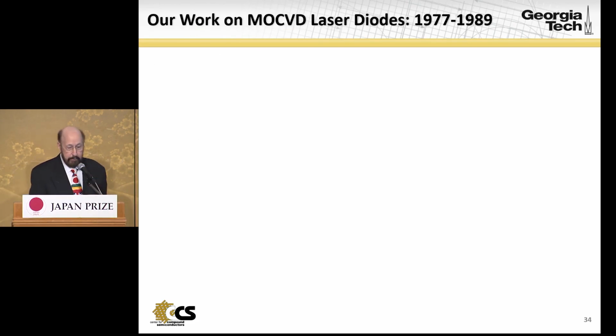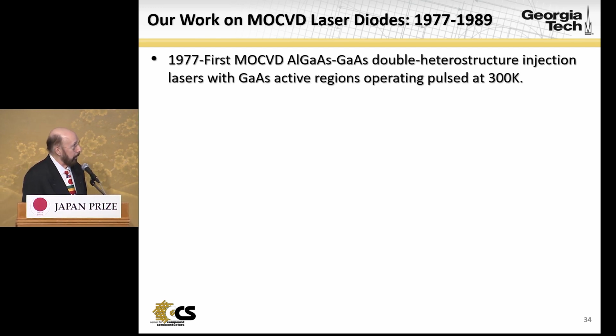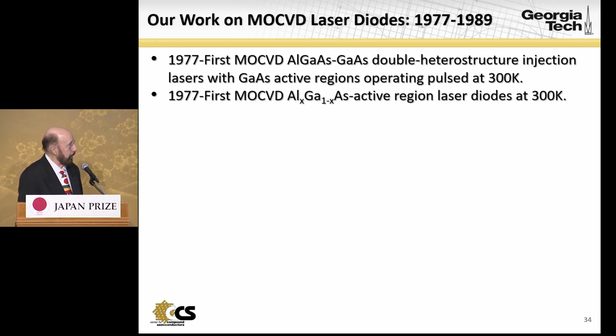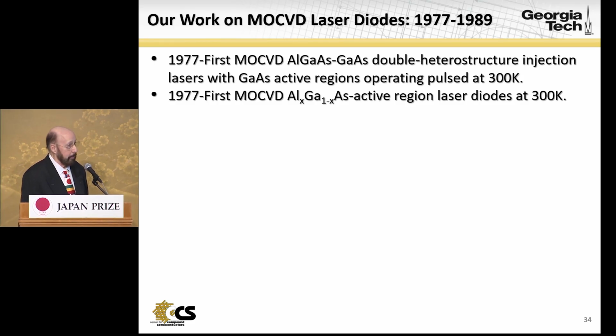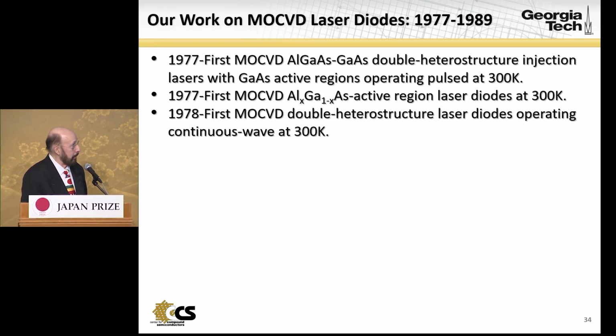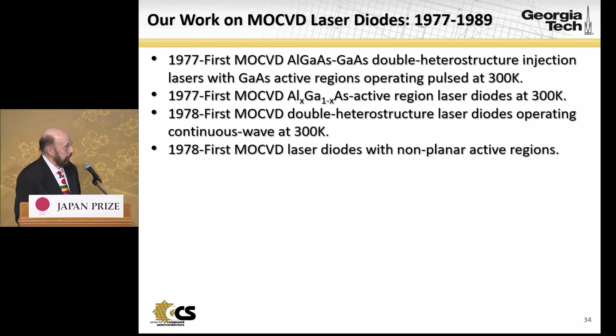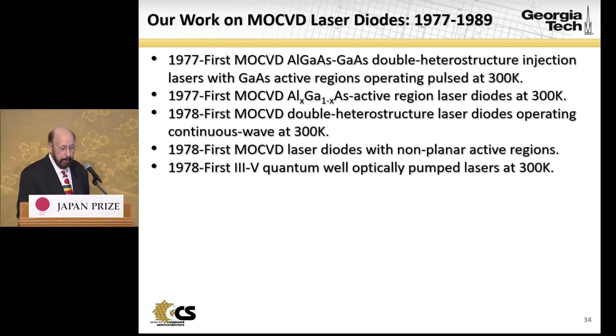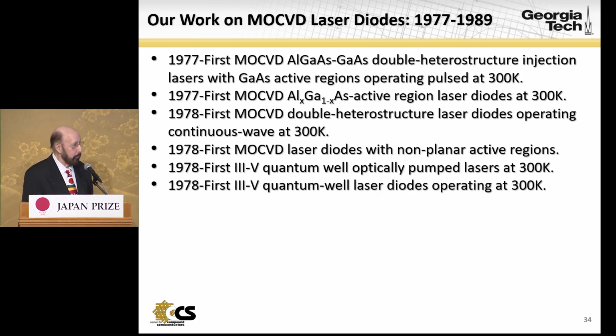So in this next period, we developed quantum well laser diodes in many different ways, beginning in 1977 with the first double heterojunction lasers with gallium arsenide active regions, pulsed at room temperature. Then the first MOCVD lasers with aluminum gallium arsenide active regions emitting at shorter wavelengths. Then in 1978, the first double heterostructure lasers operating continuous wave at room temperature. And also in '78, the first MOCVD laser diodes with non-planar active regions, the first quantum well optically pumped lasers at room temperature, and the first quantum well laser diodes at room temperature.